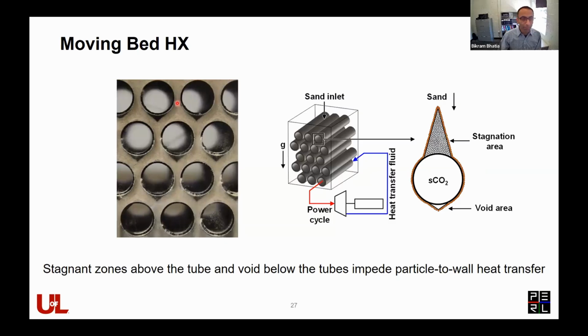So if you look at sand falling on a typical circular tube, which is a common configuration for tube bank heat exchangers, you will notice that particles actually accumulate on the top. They are sort of stagnant and they form a void at the bottom, which obviously is not great for heat transfer. So that is one of the main reasons why the heat transfer coefficient from these hot sand particles to the wall is not very high.